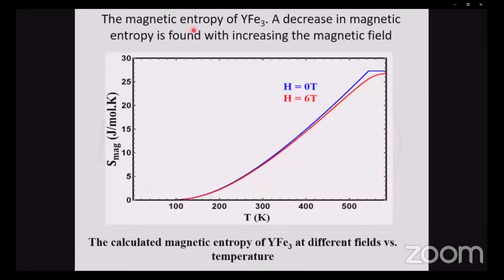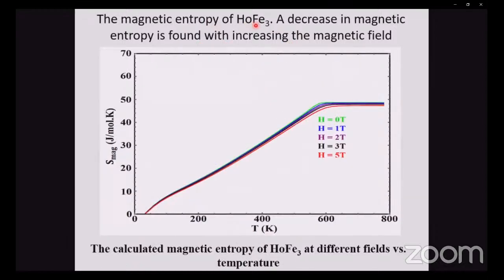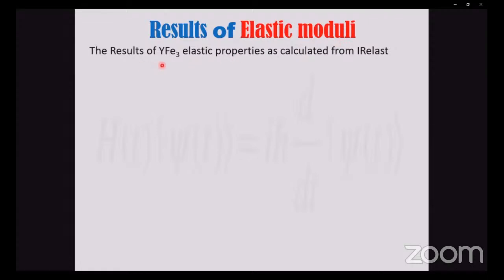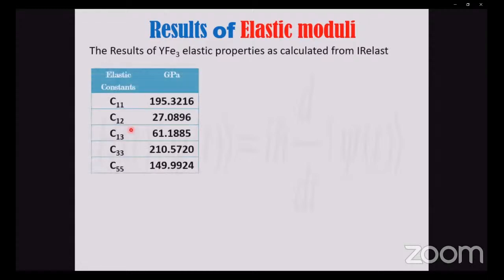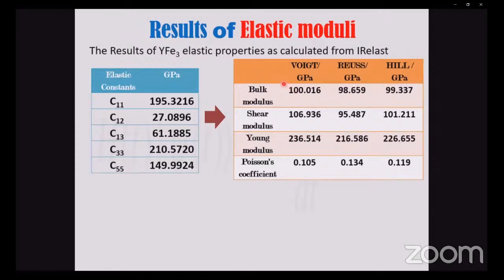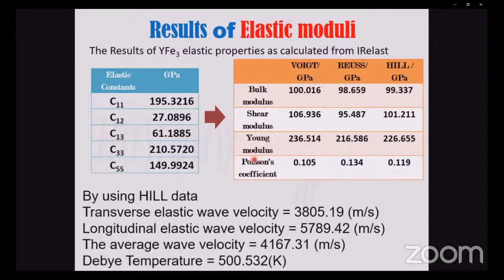The results of entropy. For the magnetic entropy of yttrium iron three, a decrease in magnetic entropy is found with increasing magnetic field. For the magnetic entropy of holmium iron three, a decrease in magnetic entropy is also found with increasing magnetic field, as shown in the figure. The results of elastic moduli. The results of yttrium iron three elastic properties as calculated from IRelast. We calculate the elastic constants from which we can calculate bulk modulus, shear modulus, Young modulus, and Poisson coefficient. These in turn are used to calculate the average wave velocity and the Debye temperature for this system.